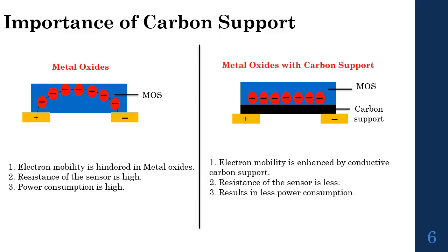Next, we are discussing the importance of carbon support. Although metal oxides play an active role in detecting gas molecules, carbon support is also equally important in gas sensor performance. Because as metal oxides alone, their resistance is very high due to less electron mobility, which leads to high power consumption. Whereas when you decorate the metal oxides on the carbon support, electron mobility is increased, which leads to a reduction in resistance and finally less power consumption.